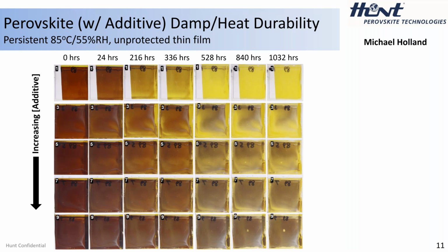It's just the bare naked material in this oven. And you can see it actually stays quite robust for up to almost 300 or so hours. It persists, but not this 1,000-hour magical marker number we like to rely on. So there's a particular additive, no, I won't tell you what it is, that we put in at an increasing concentration going down the slide. And you can see when we got to the final concentration X, the material persists for over 1,000 hours.